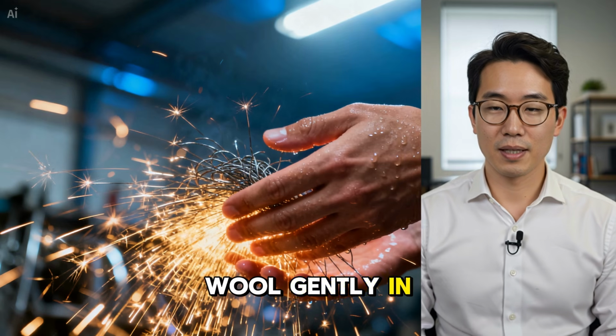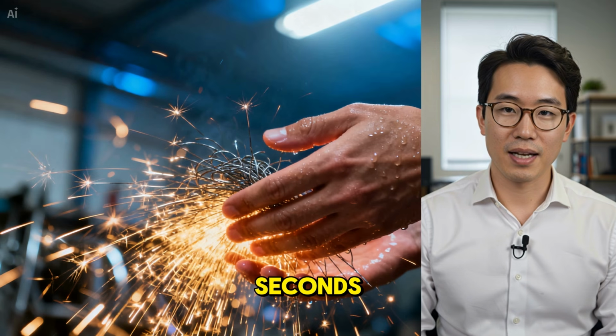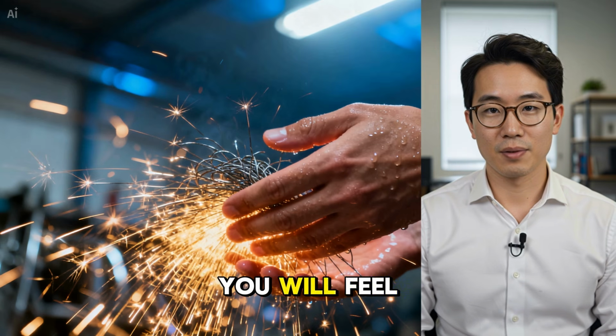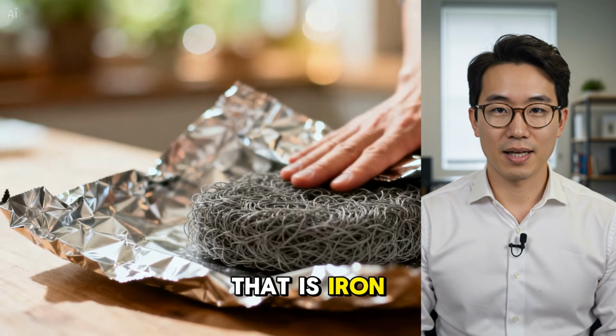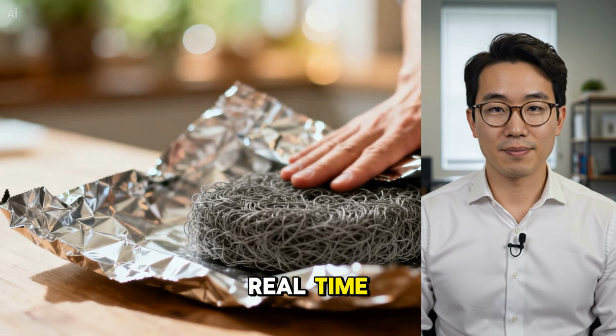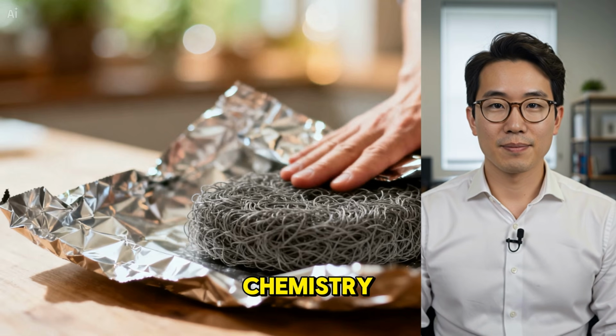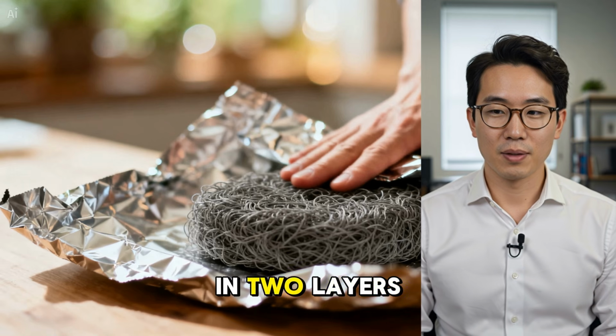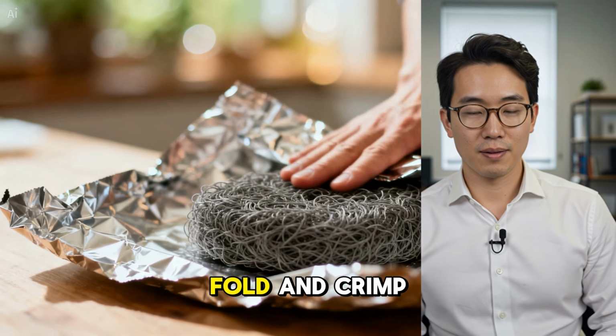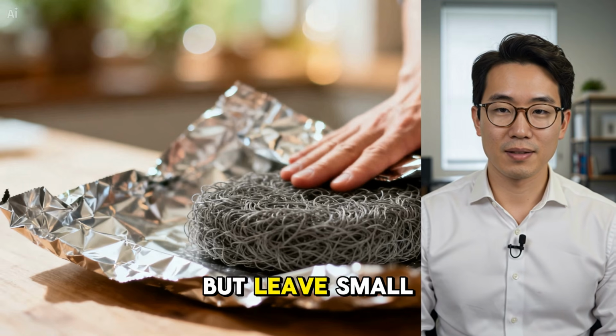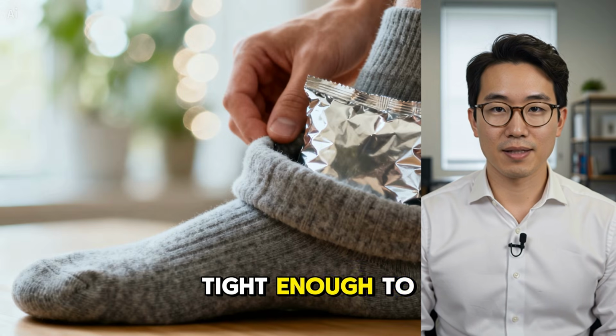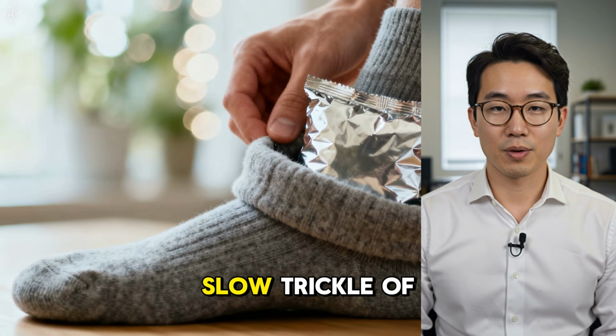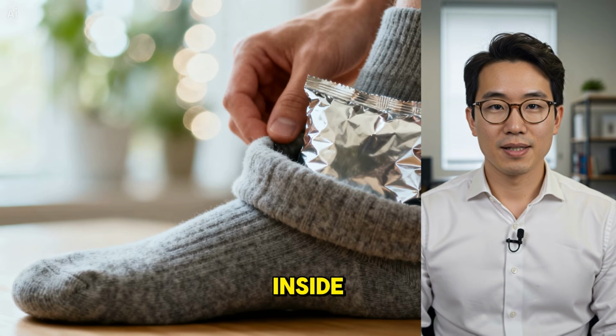Shake the damp wool gently in open air for 10 to 15 seconds. Within 20 to 30 seconds, you will feel it warming in your hand. That is iron oxidation beginning in real time. That is heat being released by chemistry. Now wrap the warming steel wool in 2 layers of kitchen aluminum foil. Fold and crimp the edges firmly, but leave small gaps at the seams, tight enough to reflect heat inward while allowing a slow trickle of fresh oxygen to reach the iron inside.